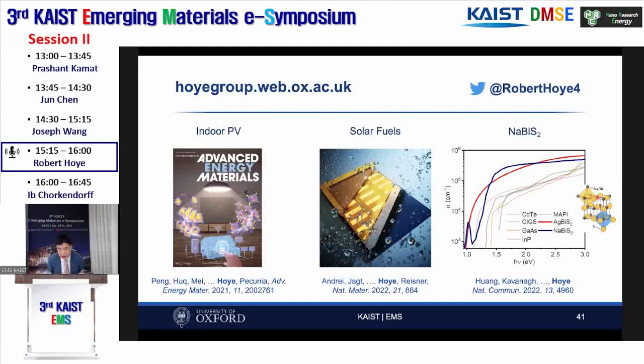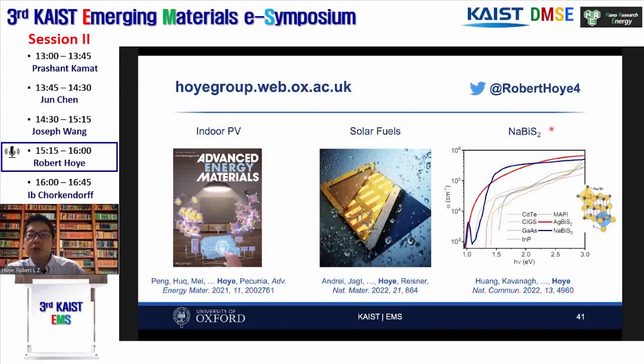Great question. So we synthesize sodium bismuth sulfide as nanocrystals. And that's because using other methods, it's very difficult to get the sodium to incorporate. So what we did here was we used sodium hydride as our sodium precursor, and we mixed that together with the bismuth and sulfur sources. And that was a method that worked quite well because of the high reactivity of the sodium hydride.